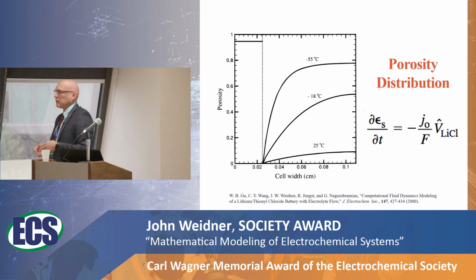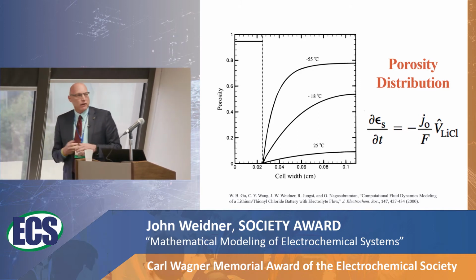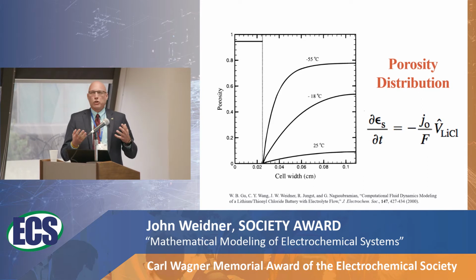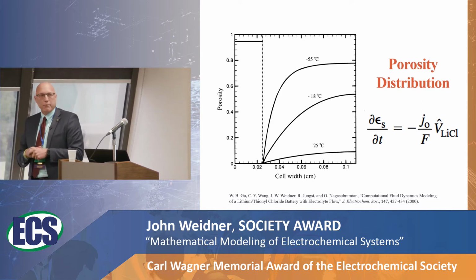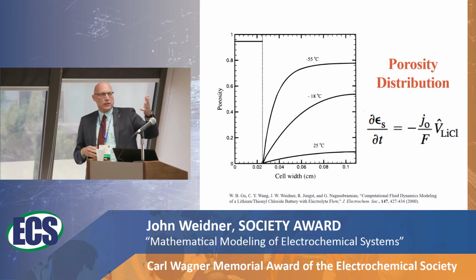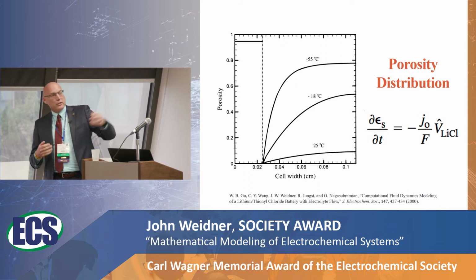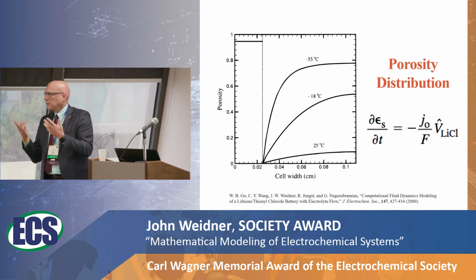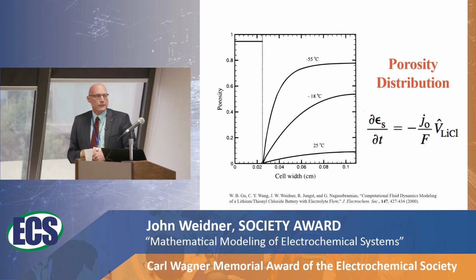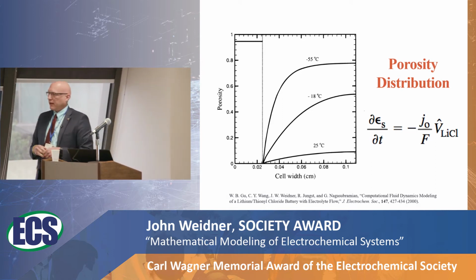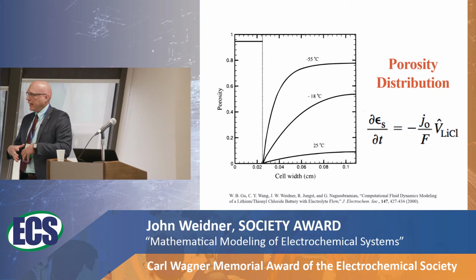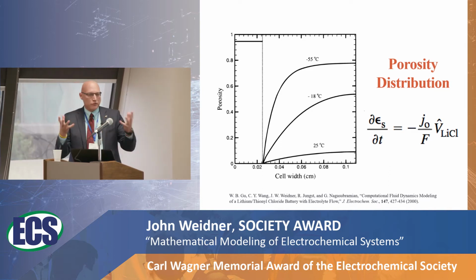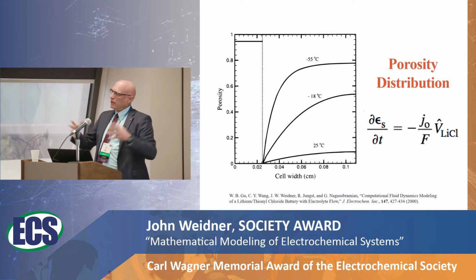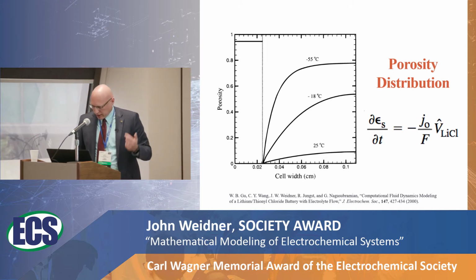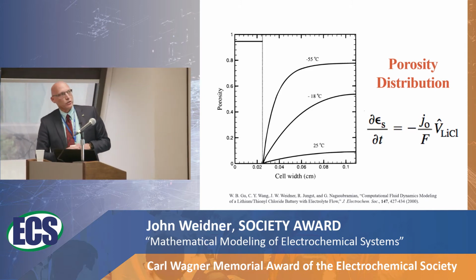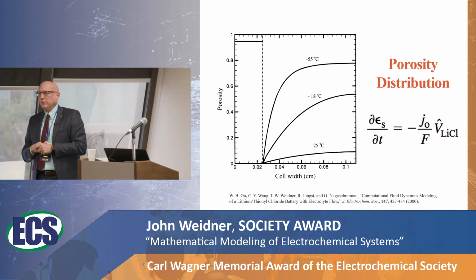However, in the model, which was fairly common in a lot of porous electrode modeling where the porosity is changing with time, you relate the porosity change to the reaction rate J, and then the volume of what's depositing, in this case the lithium chloride. And so it was saying any deposition that was occurring was filling pores, but then what was causing the electrodes to expand? So we started thinking about this over time, and we looked at a kind of generic system.